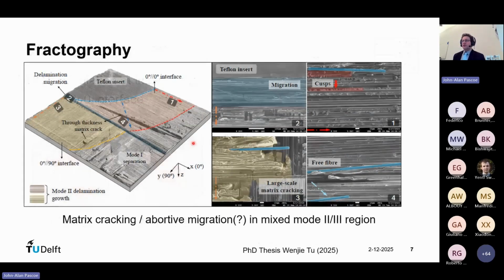And this is what it looks like then if you open up the fracture surface and look from the top. So we have over here the migration boundary, here an area where there's the pure mode 2 growth, here an area of pure mode 2 growth as well, but then in the 90-degree direction. And in between we have this region where we see some matrix cracking, but not full-blown delamination yet. So not full-blown migration yet. So the delamination is trying to migrate, but it's still being blocked. It can't break all the way through, but it is diving into that adjacent ply.